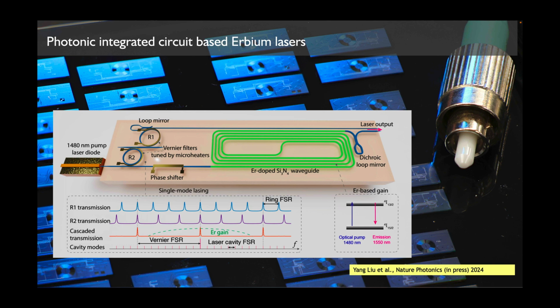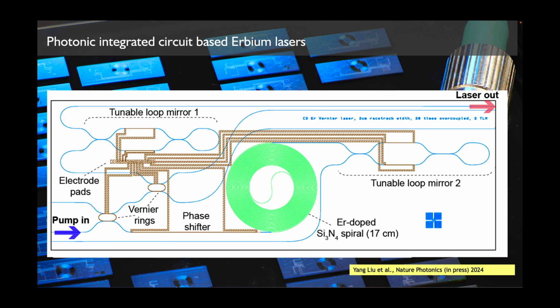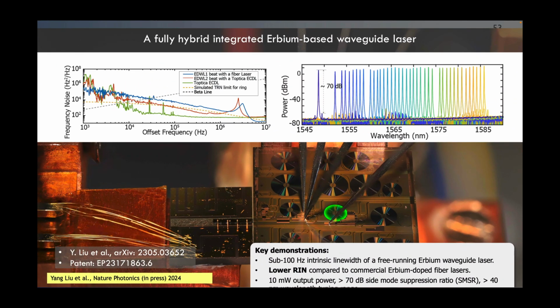You see here a silicon nitride circuitry. You see resonators that form frequency selective elements that you can tune very fast with either heaters or piezoelectrics. And you see here selectively implanted erbium gain. So that's the rendering. The actual chip looks like this, and you can do selective implantation only in regions where the erbium needs to be. In this case, in our long gain spiral. And you see here the circuit layout, including the verniers and the reflectors. And with this, we can make lasers that are fully tunable across the C and L band, with very high side mode suppression ratio, and also reasonably low phase noise. So again, showing that you can make erbium doped waveguide lasers that have the same kind of performance as conventional ITLA lasers used in telecom.